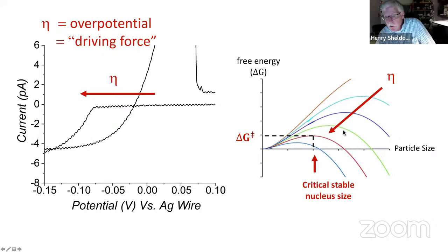And these curves are for different overpotentials. This teal colored curve right here is at a low overpotential, and the red one down here is at a high overpotential. And nucleation theory is a very classical model here. It says there's an activation barrier, right? There's an activation energy associated with nucleating a new phase.